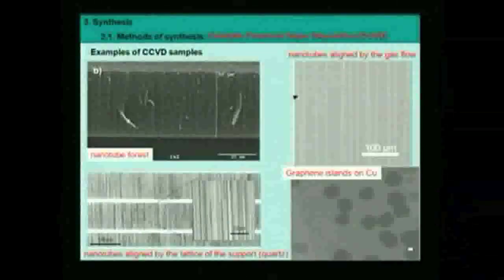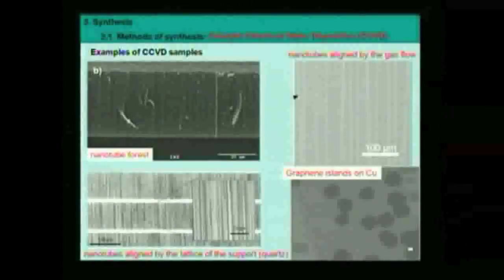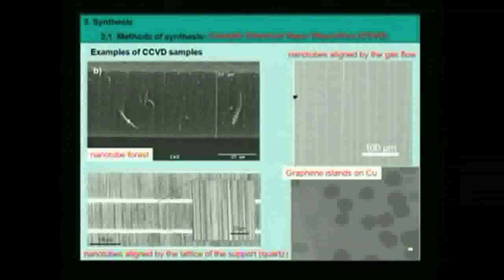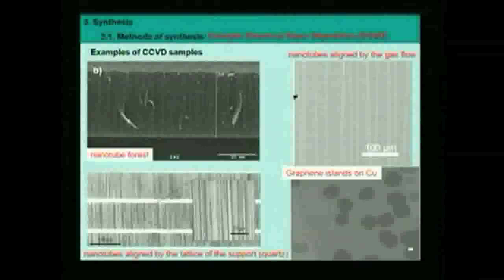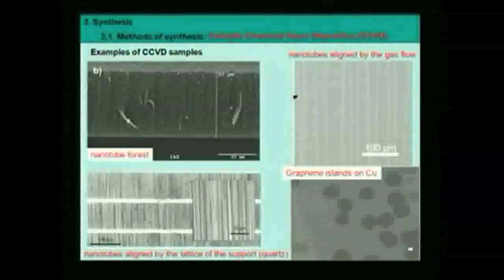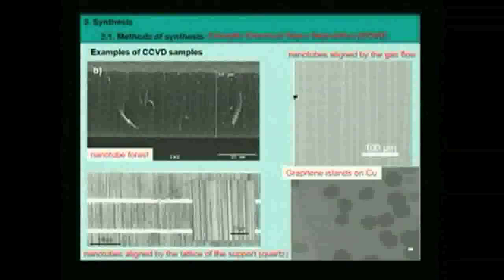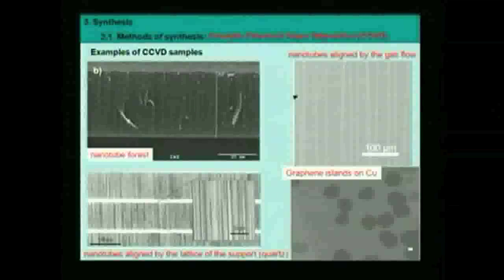So in special conditions, where you have a proper balance between this forced convection induced by the flow and the natural convection from bottom to top, which is also called buoyancy, this natural convection toward the top and the forced convection toward one side, then if you have this proper balance, you can have nanotubes growing in the gas phase and oriented by the gas flow. This is called kite growth. Kite is a tool that children use on the beach when there is enough wind. So I don't know the word in Spanish. Kite. Kite, you know? Cerf-volant. Parapaillo. Oh, okay. So this is called kite growth, oriented by the gas flow.